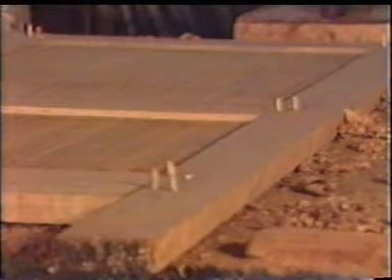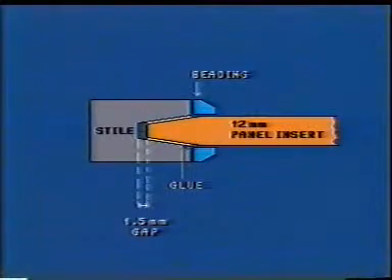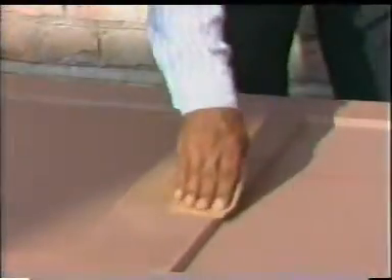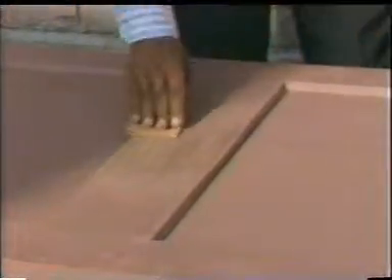Check that all joints have two bamboo pins each in a staggered position. Open a sample door to check that edges of panels fit in the groove, leaving an air gap of 1.5 millimeters for expansion. Beading should be provided at the junctions. Scrape the priming coat at certain locations for checking its evenness. The species of wood should also be checked at this stage.